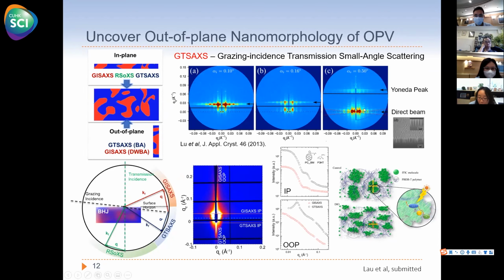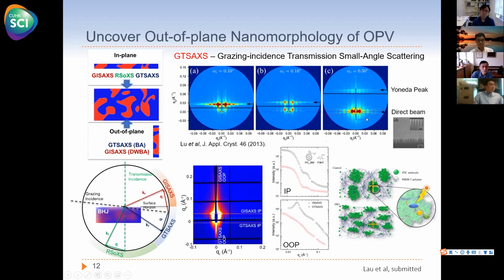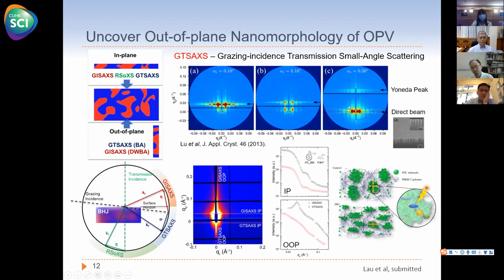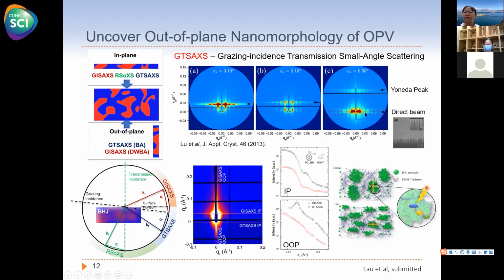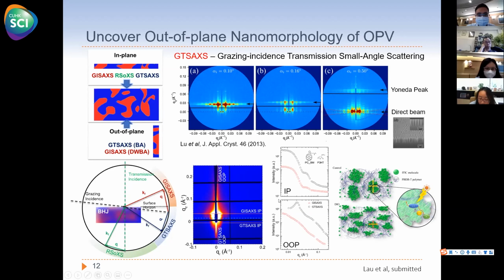By doing this, we can produce a very nice, beautiful, symmetric scattering pattern below the horizon. Okay. So when we apply this technique to the bulk heterojunction, we can simultaneously obtain in-plane and out-of-plane nanophase separation information for the first time.